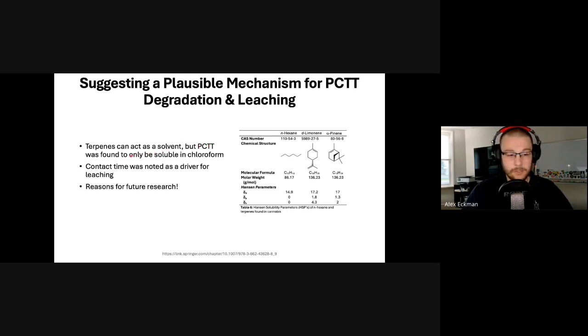The other thing too was, although our sample size was incredibly small, we did notice that contact time was a driver for leaching, with the higher leaching vapes being aged above 250 or so days. And it seemed to be an exponential rate of return on the leaching after about that year point. So we don't really know if it's a cannabinoid, a terpene, or just contact time causing this, but I think it's a cause for future research.